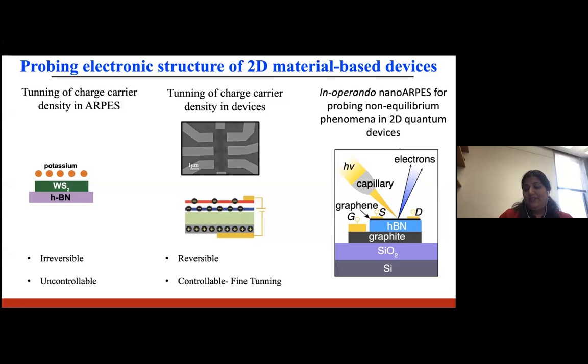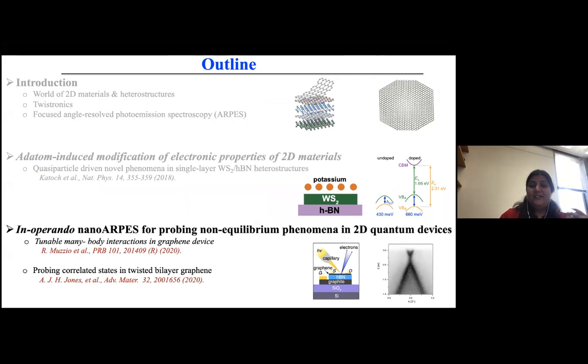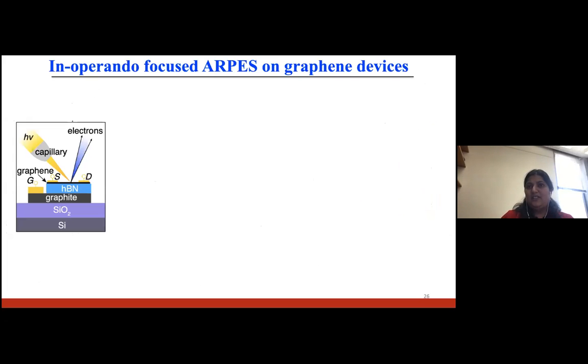So in the last 2 years at Carnegie Mellon, we have been pushing in operando nano ARPES measurements on fully functional devices. In such a setup, we can simultaneously measure the energy and momentum resolved electronic band structure of the 2D materials while we're applying backgate voltage or passing current to the sample. Now I'm going to show you our in operando nano ARPES results, where in the first study, we demonstrated tunable many-body interactions in graphene devices. And here, the spot size for our ARPES was about 2 microns.